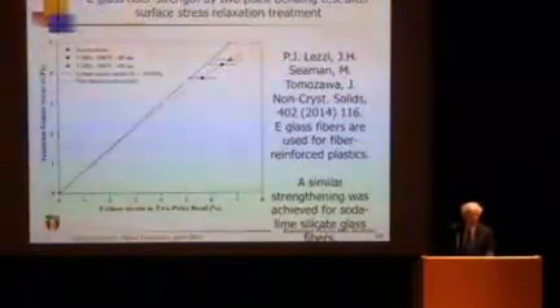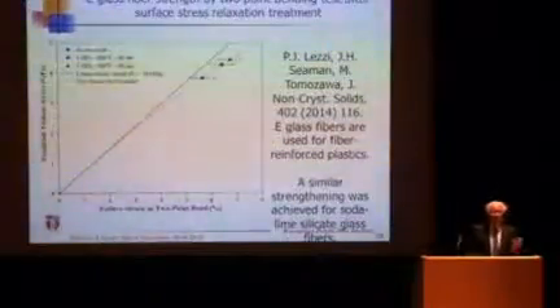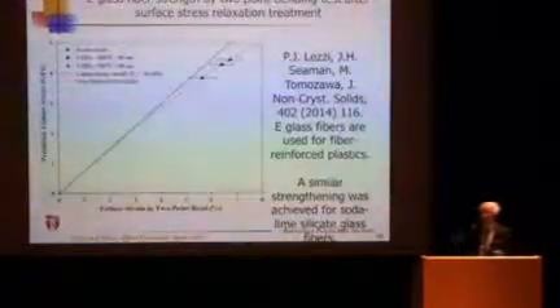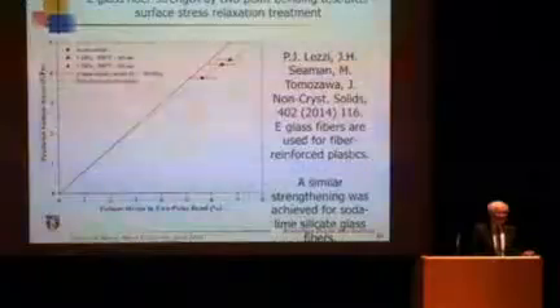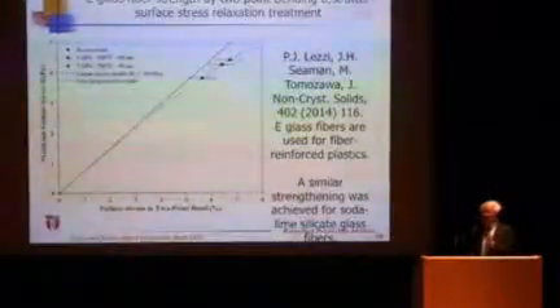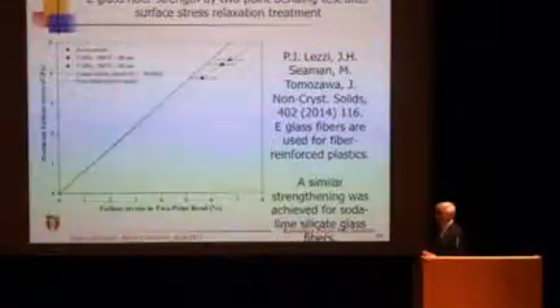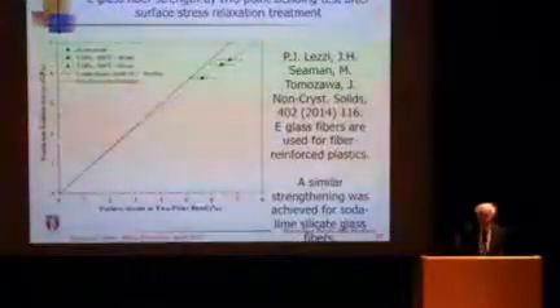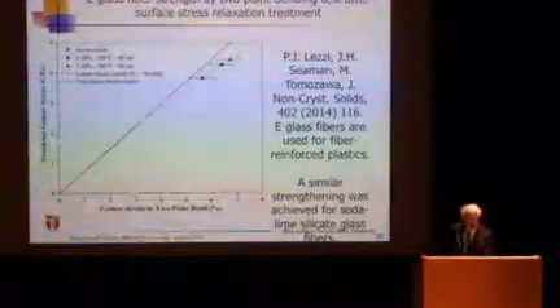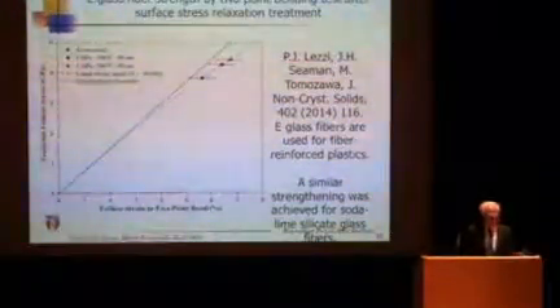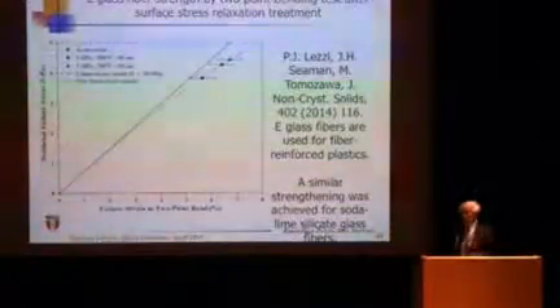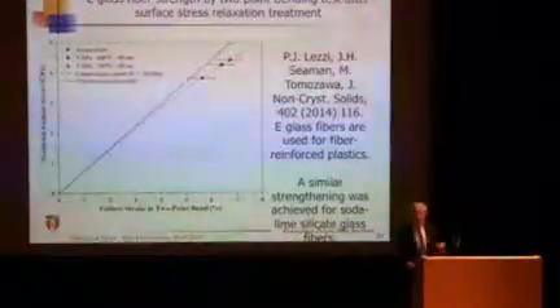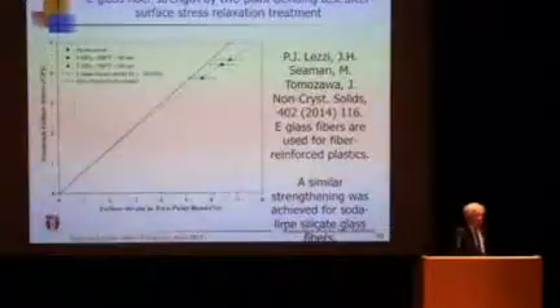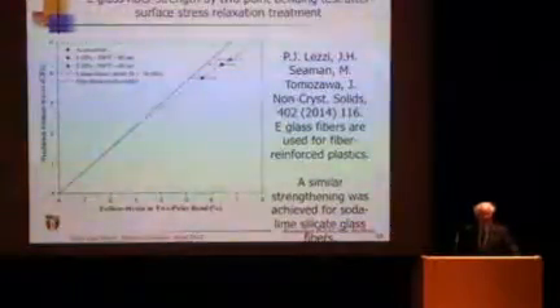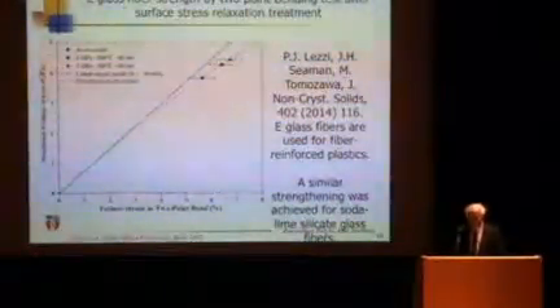And the advantage of this method is it is not limited to a minimum thickness. We don't need 3 millimeters, and we can also do without any alkali, because the glass composition is irrelevant. And we also did this for soda lime glass. So far we did silica glass, E-glass, and soda lime glass fiber. All can be strengthened. I believe all the oxide glasses can be made stronger by this method.